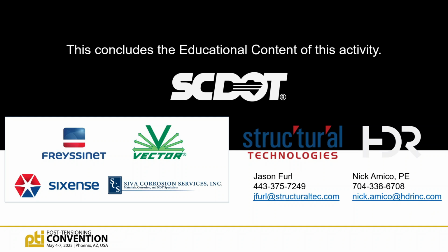Now, there are some limitations. It can only scan in the free length. You can't get into what goes into the bottom slab, top slab, or more importantly, what's inside those deviators, or diaphragms rather. And then for the capacitive probe testing, again, kind of the same story. We didn't find significant issues with it. We found a lot of voids, but more often than not, it was a really small void that runs along the top side of the tendon that's just not an issue.